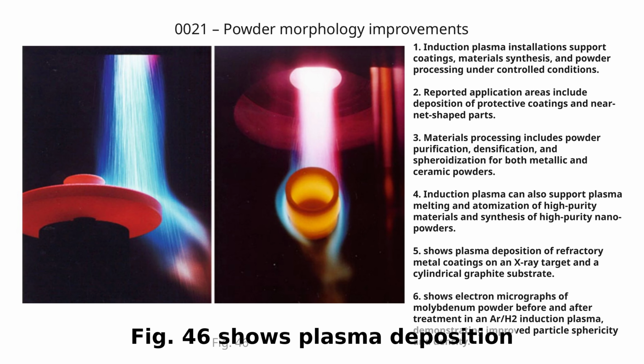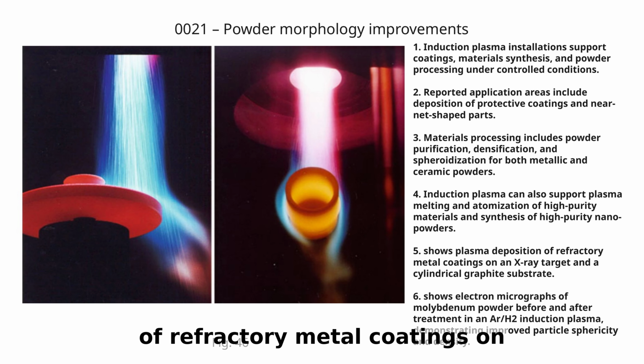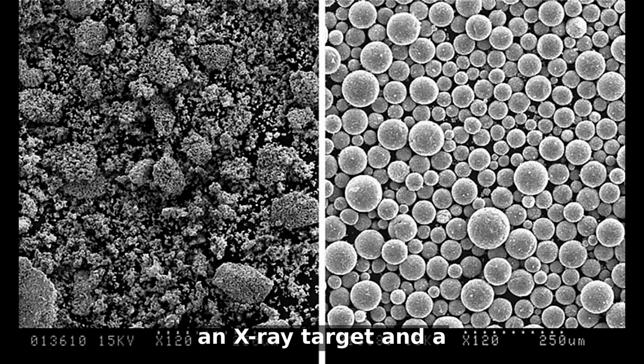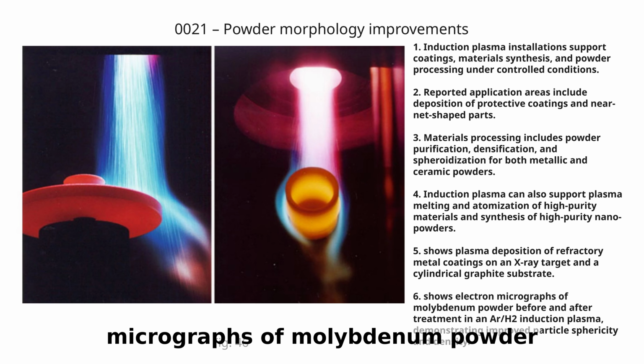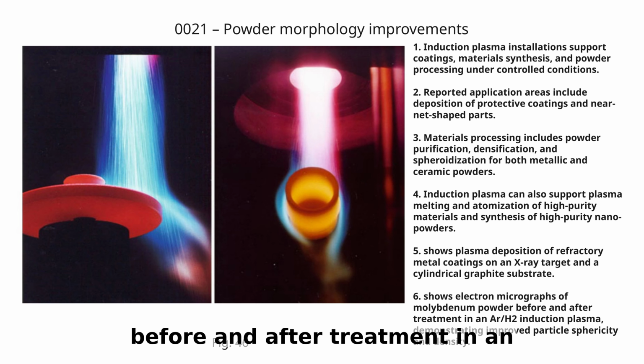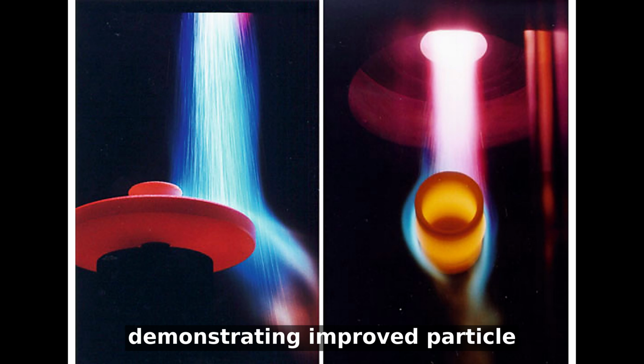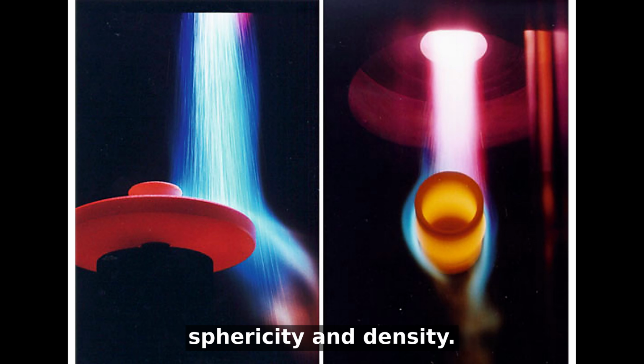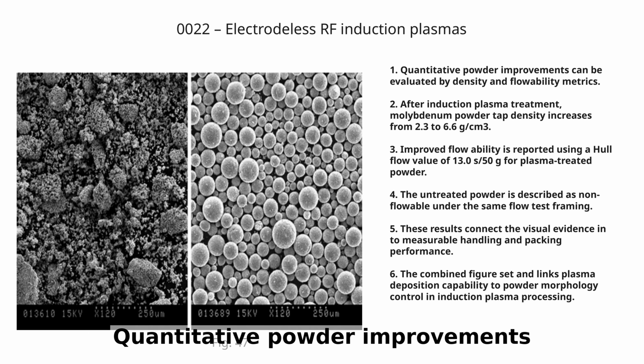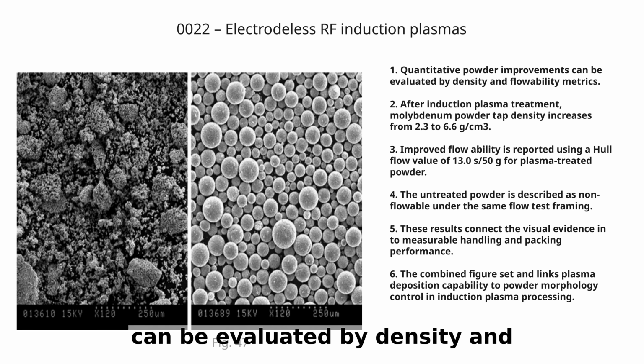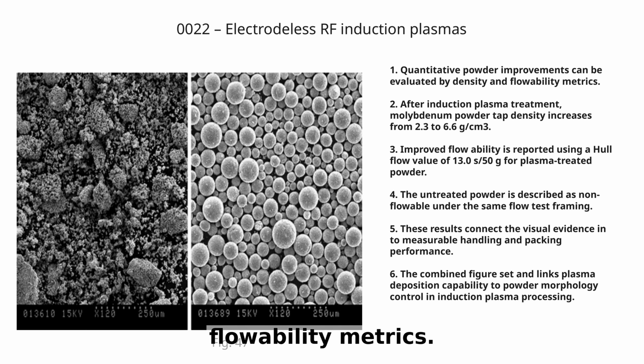Figure 46 shows plasma deposition of refractory metal coatings on an X-ray target and a cylindrical graphite substrate. Figure 47 shows electron micrographs of molybdenum powder before and after treatment in an induction plasma, demonstrating improved particle sphericity and density. Quantitative powder improvements can be evaluated by density and flowability metrics.